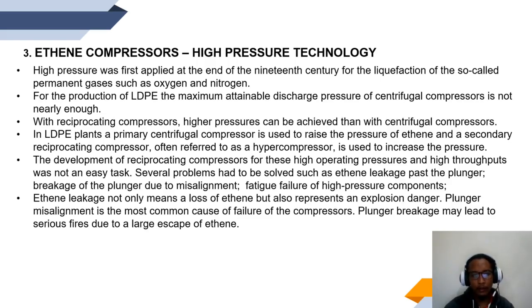The development of reciprocating compressors for these high operating pressures and high throughputs was not an easy task. Several problems had to be solved, such as ethene leakage past the plunger, breakage of the plunger due to misalignment, and fatigue failure of high pressure components. Ethene leakage not only means a loss of ethene but also represents an explosion danger. Plunger misalignment is the most common cause of failure of the compressors. Plunger breakage may lead to serious fires due to a large escape of ethene.